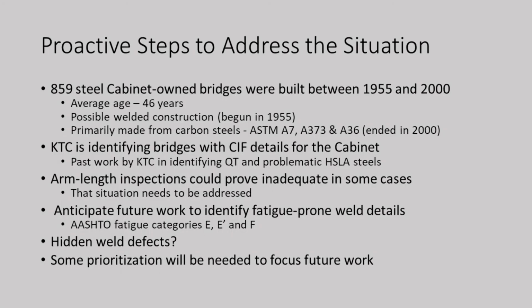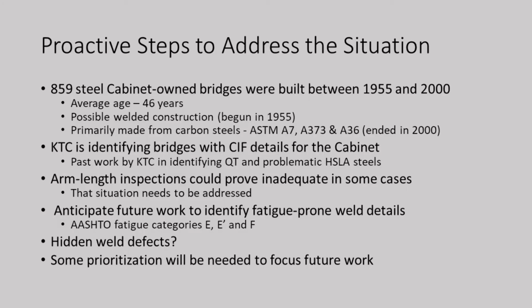Currently, we are engaged in an SPR research study identifying bridges with CIF details for the cabinet. We're pretty close to wrapping that up. In the past, we went through and identified all the quenched and tempered steels and potentially problematic high-strength, low-alloy steels as well. The issue of this arm's length inspection needs to be studied a little bit: when can you get away with it, and when does something else need to be used. We do anticipate future work to identify fatigue and fracture prone details. Average age of our bridges is about 46 years, so it falls in that 40 to 60 category we saw for the 3 fractures we encountered.